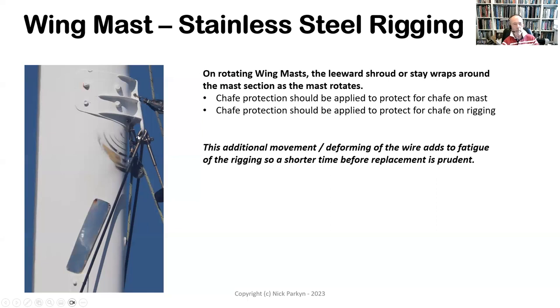It's not under load, but of course, remember that you have a fairly stiff terminal, for example, here, a rigging terminal. And then you're constantly changing the angle of that quite dramatically. And again, the one thing is the chafe on the spar itself. And then the other thing is that the additional movement obviously deforms the wire, especially the lay of the wire, and of course adds to the fatigue that you would get over time in the rigging. And so with the rotating wing mast, a shorter time before replacement of the rigging would probably be more prudent in my experience.